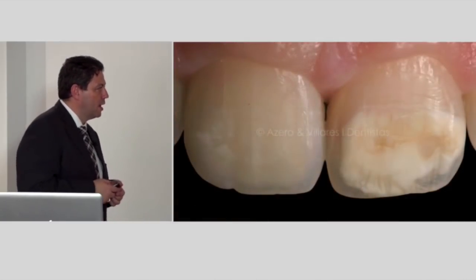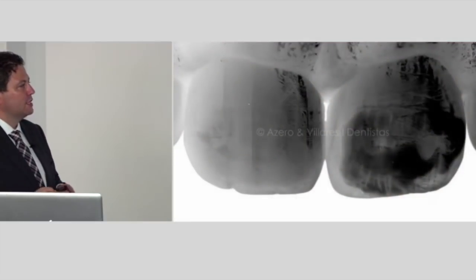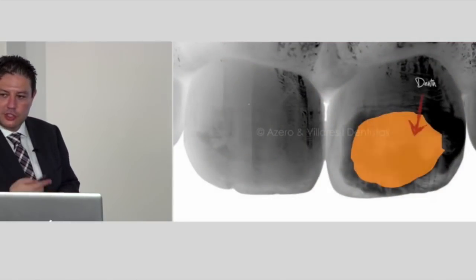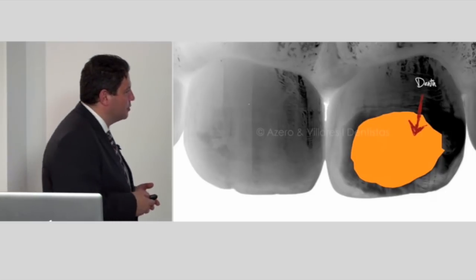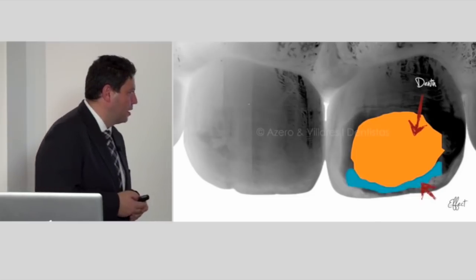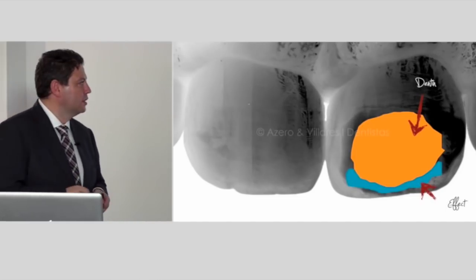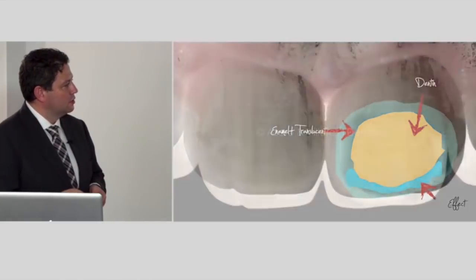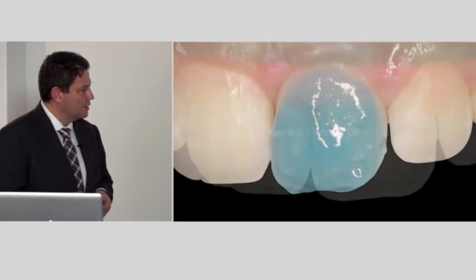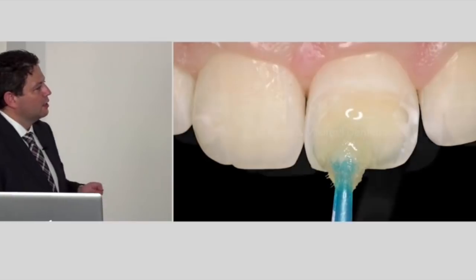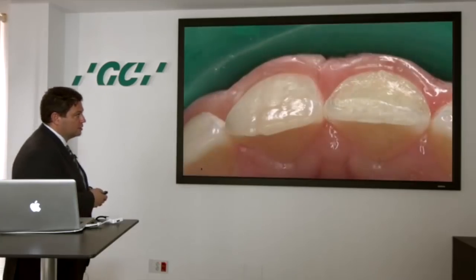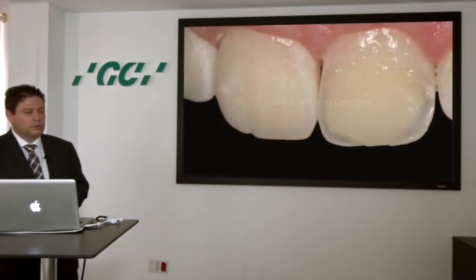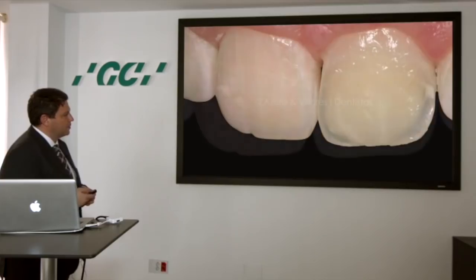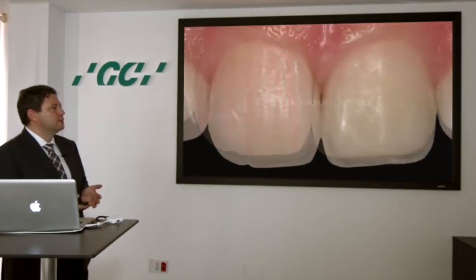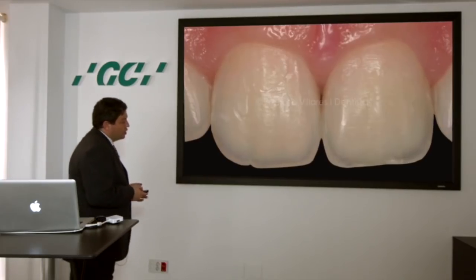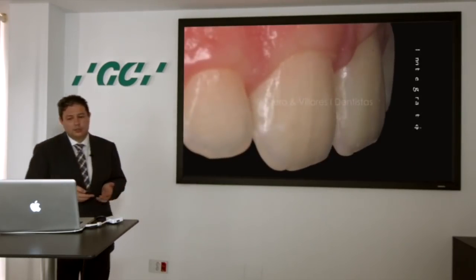This is how it was prior. What we always do is a protocol that we're going to mention during the webinar. We put the dentin, some effects, the enamel, translucent. It's very important to follow the rules: apply the acid etch, the adhesive, know what material you're using, apply, and control the thickness. Very, very important to control the thickness. Now we have tools that allow us to control the thickness more easily. And of course, reproduce the dental anatomy after finishing and polishing, and try to imitate as much as possible a restoration that integrates in the mouth.